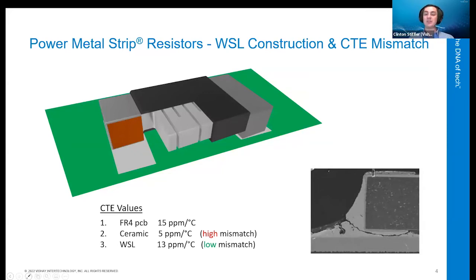Because of the CTE mismatch and the solder joint fatigue issues of the ceramic chip resistors, automotive designers have rules to limit their use to only smaller sizes, such as 0805 or smaller terminated footprints. Now the WSL, all metal welded construction, has a CTE of 13 parts per million per degree C. And because it does not depend on the rigid ceramic substrate, it has a rate of expansion that is more comparable to the CTE of FR4. Since it does not have a large CTE mismatch as compared to the FR4 material, it has better long-term solder joint performance. For this reason, the WSL product has been chosen in automotive applications in the larger, higher power footprints, such as 2512, 2010, and 1206 sizes, where ceramic is forbidden.